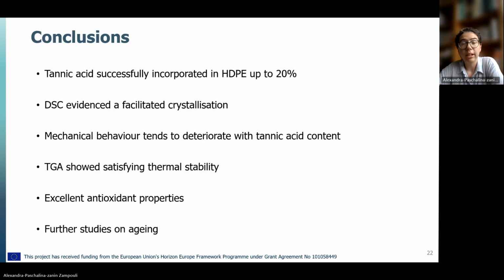So to conclude, tannic acid was successfully incorporated into high-density polyethylene up to 20% by weight. DSC evidenced a facilitated crystallization, but further studies are ongoing to confirm this observation. Mechanical behavior tends to deteriorate with tannic acid content. Thermal stability was satisfying, and the composite exhibited excellent antioxidant properties. Further studies on oxidative aging, and whether it can be delayed by the presence of tannic acid, are ongoing.